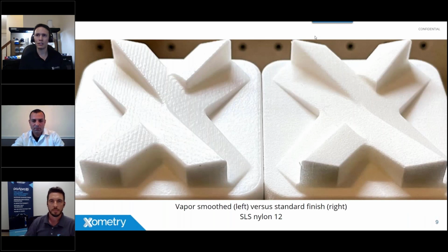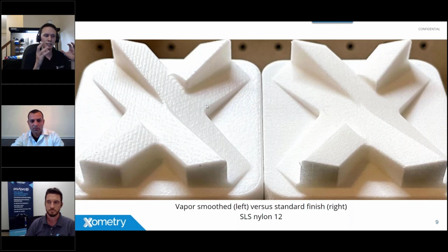And I got some examples here, just showing some images. And actually, these are some of the parts behind me here. This is selective laser sintering, and the item on the left is a vapor smoothed piece. The surface, you can see it's not polished, and we try to stay away from the word polish for a few reasons. But what it's done is sealed that surface and mitigated a lot of the coarse layer features. Even when you feel this, it feels like a molded plastic piece. You don't feel that surface roughness on it.